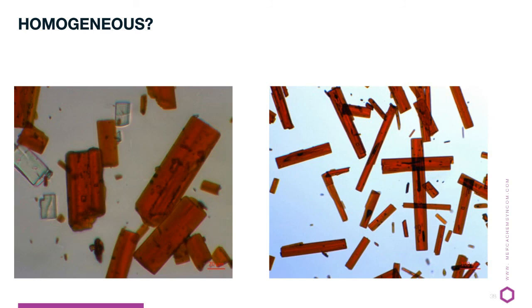We had to do some recrystallization of this compound, and as a result, seen to the right, the crystals grown longer. These are much larger than obtained when the impurity was present. In this case, an additional micronization step was required to get a good material that could be formulated.